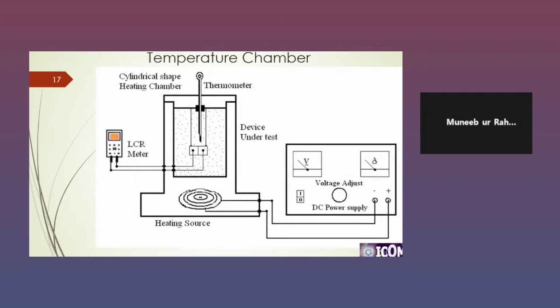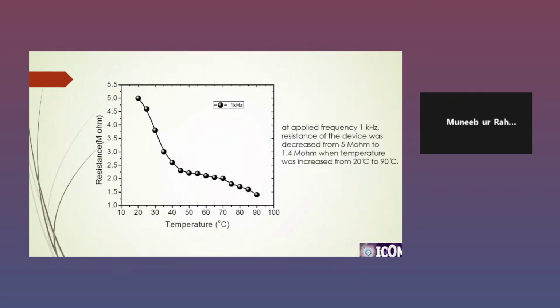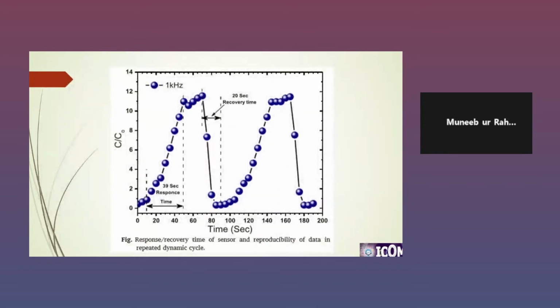This is the temperature measurement setup, and this is the resistance with temperature, showing how the resistance of the sensor decreases with temperature. And this is the response and recovery time. The quicker the response and recovery time, the more quickly we can use the device for the next measurement. In this case, we noted that our response time was 39 seconds, and the recovery time of our device was 20 seconds.